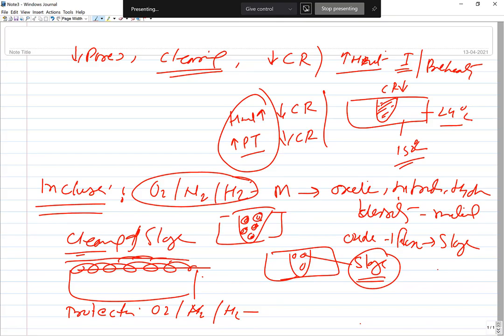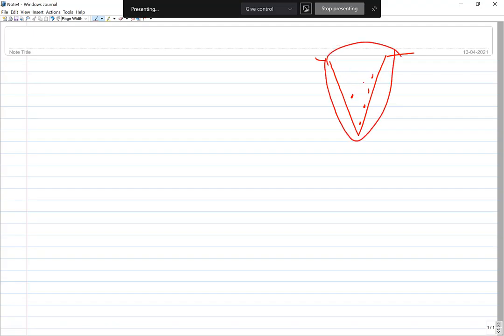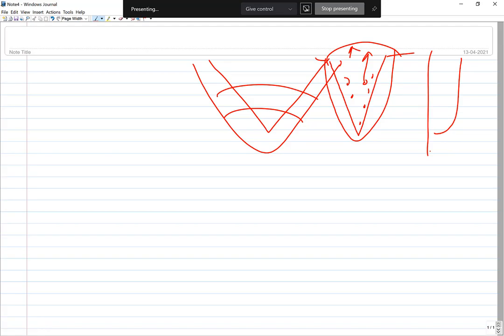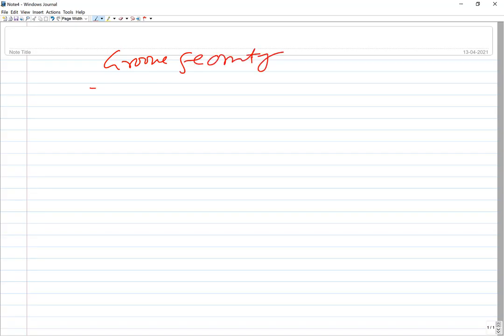There is another possibility related to groove geometry. If your weld geometry is a narrow groove, it will take very long for inclusions to reach the surface. A J-groove or U-groove geometry will have a greater tendency for entrapment compared to geometries that are wide and open, allowing slag to float up to the surface. Choice of suitable groove design can also help control inclusions.